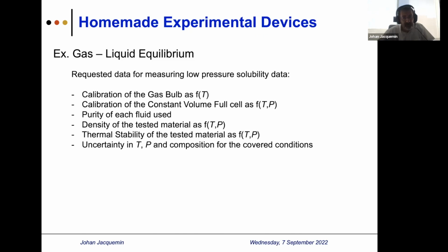The thermal stability of testing material must be known, which somehow could seem stupid. But if you are using a porosimeter and you have to dry your solid sample, sometimes you dry it under vacuum at 100 or 200 degrees C for 12, 24 hours to be sure that it's dry enough. But sometimes your material decomposes under such a condition. So uncertainty in temperature, pressure and composition must be known as well.